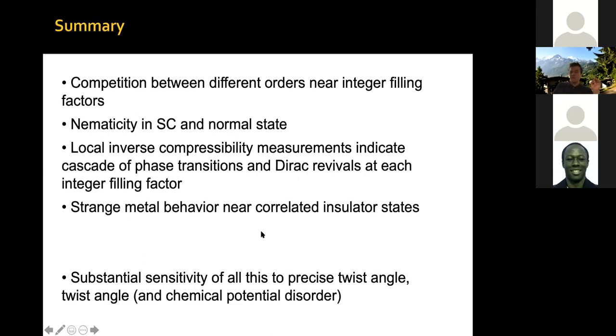Now, I should mention that all of this has substantial sensitivity to the precise twist angle, okay? If nothing else, the band structure itself in the theoretical calculations for Magic Angle Graphene is extremely sensitive to twist angle on 0.01 degree twist angle increments, okay? So Magic Angle Graphene is actually a magic angle range. There's a range of magic angles, or a range of angles for which the magic happens. And the magic can manifest itself quite differently depending on the precise twist angle, okay?